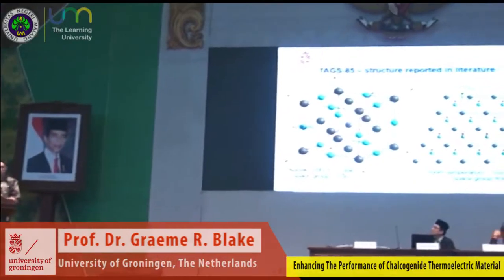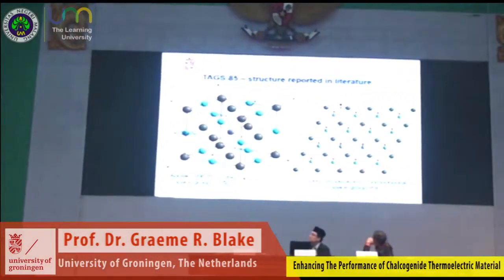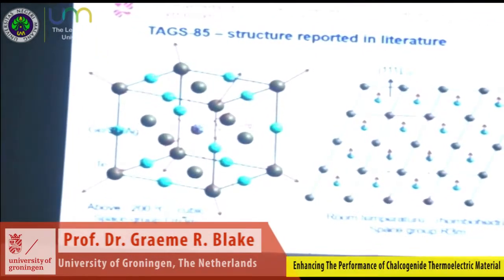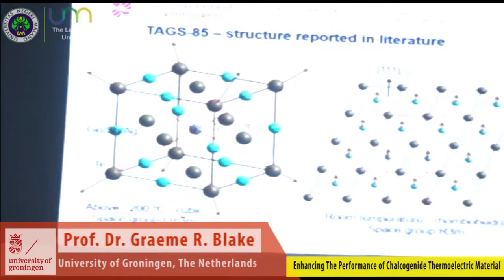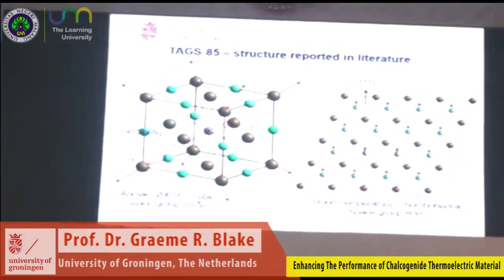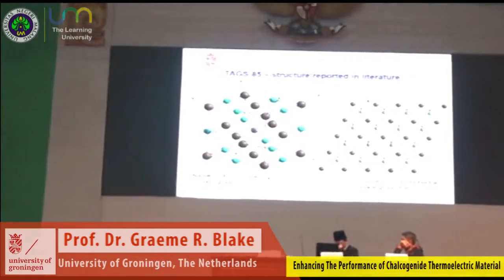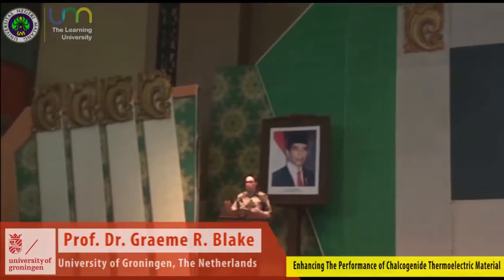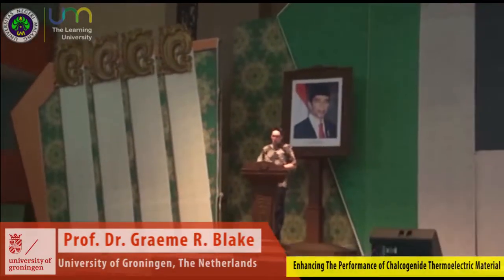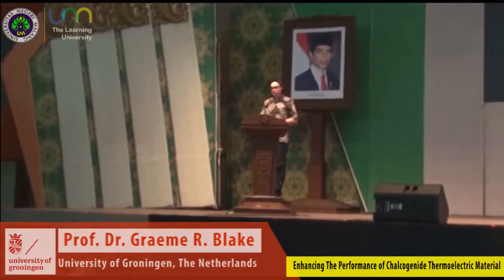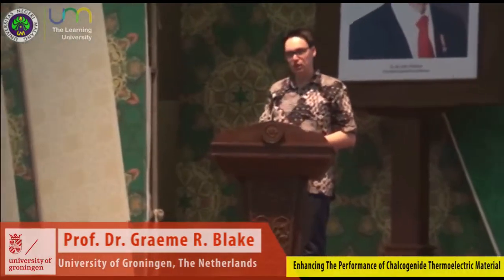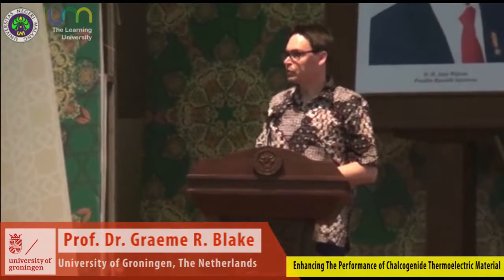So that breaks some of the symmetry, and you are left with a rhombohedral symmetry, which has a unique direction corresponding to the stretching direction of the cube. Now, of course, there are 4 body diagonals in a cube, so you can stretch it along any of these 4 diagonal directions, and this gives rise to the formation of these zigzag domains. So it's a naturally formed nanostructure which forms on small length scales of tens or hundreds of nanometers, and it scatters phonons very well. Next, please.